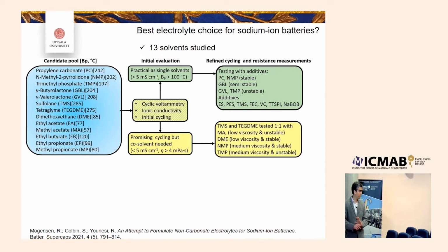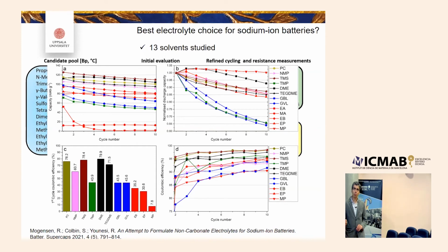I'm not going to go into the details of all these electrolytes here, it takes a long time, but I thought to put just a snapshot of the results where you could see that some of these electrolytes, like sulfone-based electrolytes, do give quite high Coulombic efficiency on the first cycle and also relatively stable cycling. Some of them, as I said, have been neglected because they're not that interesting for lithium-ion batteries, but they may provide opportunities for sodium-ion batteries.